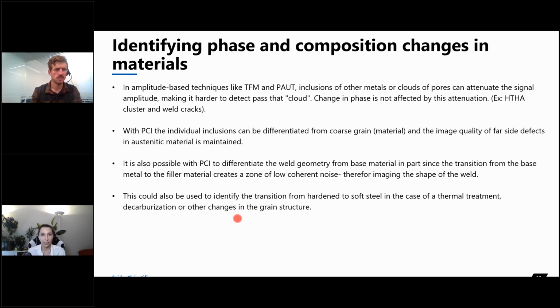With PCI, the individual inclusion can be differentiated from coarse grain. So we kept mentioning that we can really see small defects. Sometimes people ask us, will I see all the grain and will I know the difference? Yes, it will help you see inclusions from what's grain structure. And the image quality of far side defects in austenitic materials is maintained as well. Sometimes penetrating through that thick or coarse weld material can be challenging with an amplitude technique, but with PCI, we see a lot of benefits there.